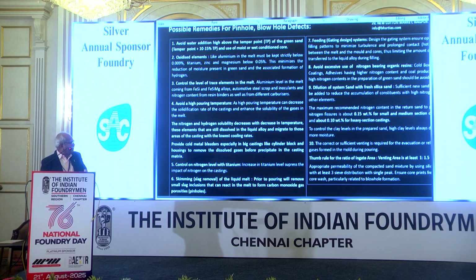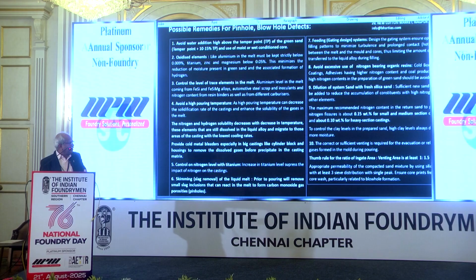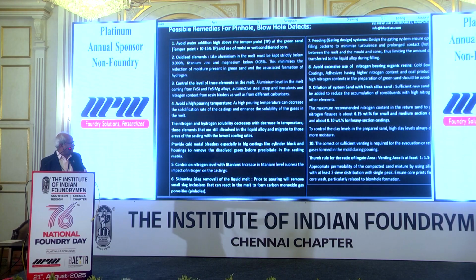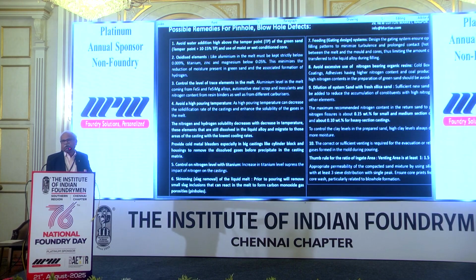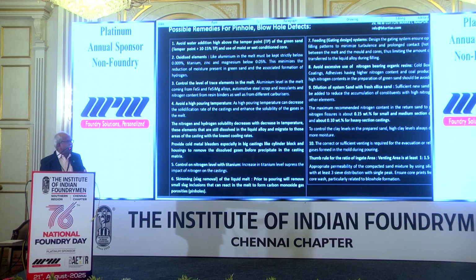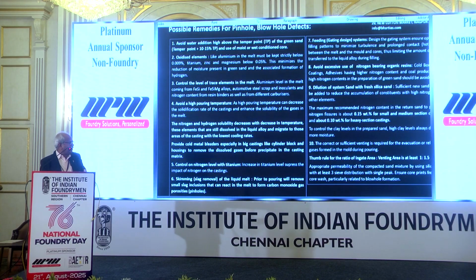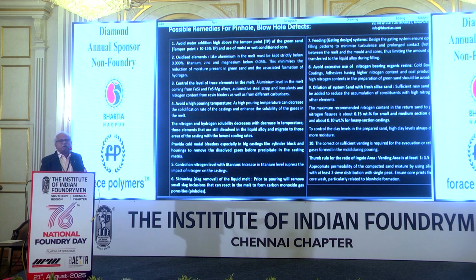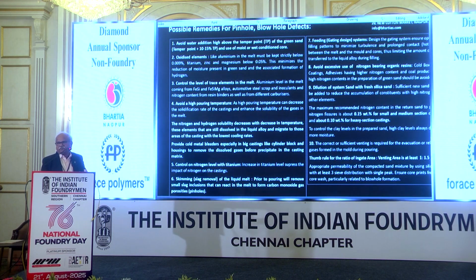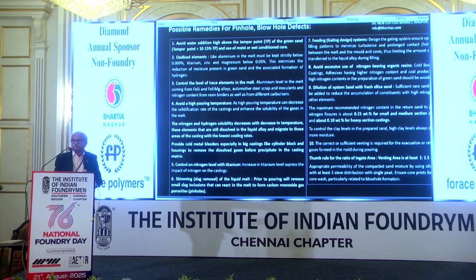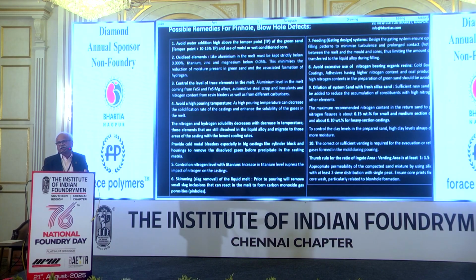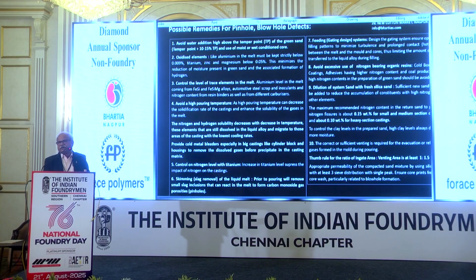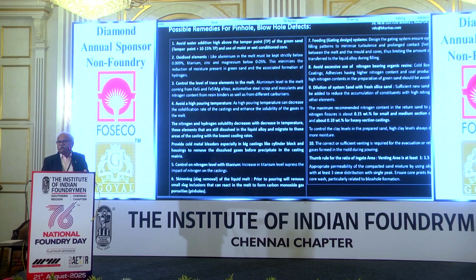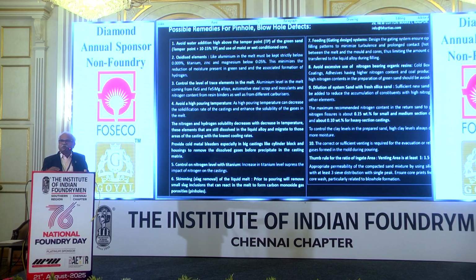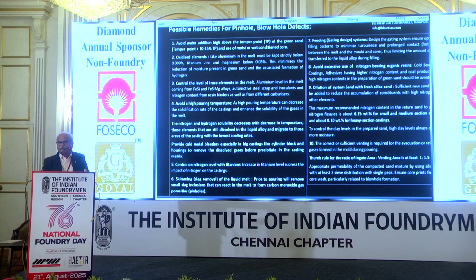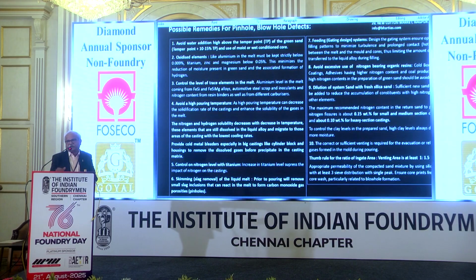Correct and sufficient venting is required for evacuation of the gases formed in the mold during pouring. The thumb rule for the ratio of ingate area to venting area is at least 1:1.5. That means if the ingate area is 100 mm squared, then we need to maintain at least around 150 mm squared of venting area, to release the pressure inside the mold and control the defects.